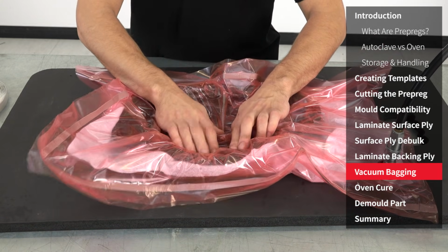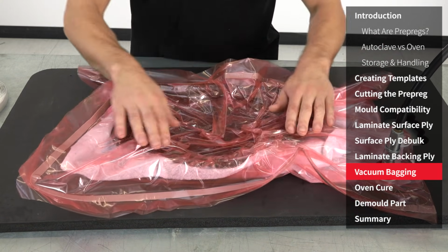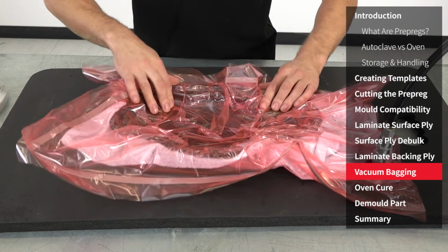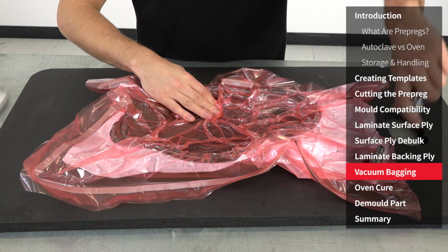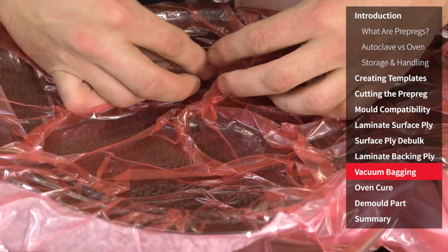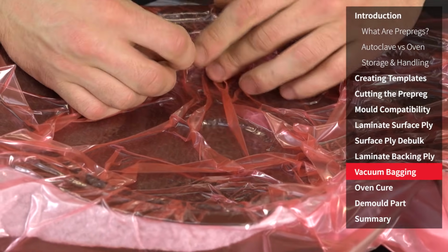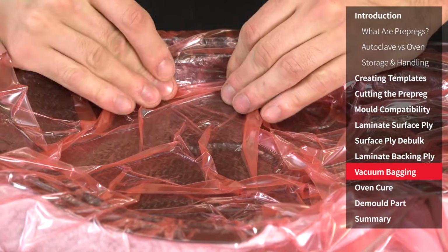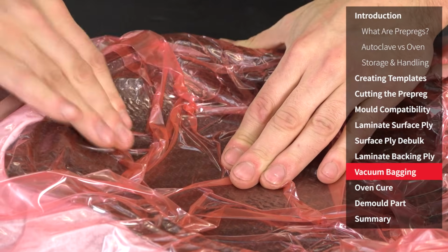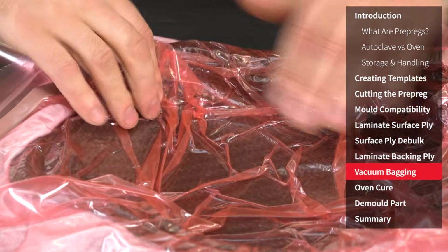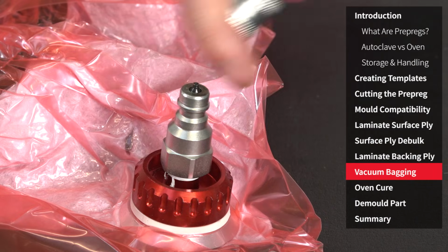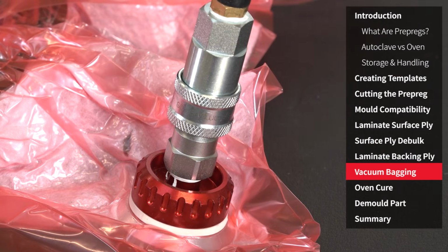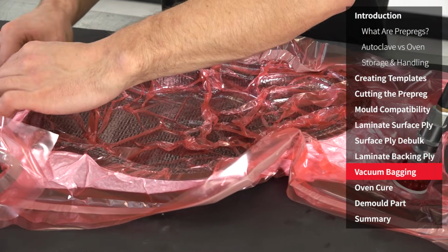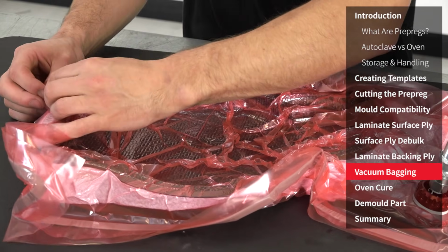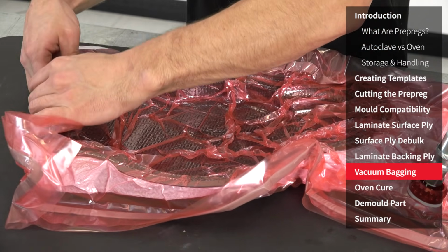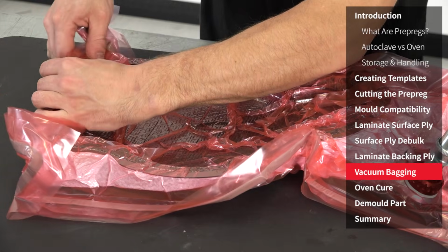As the vacuum is pulling down, the bagging film should be manoeuvred and manipulated so that it conforms to the laminate without having to stretch. You will normally need to disconnect the vacuum supply a few times to allow for repositioning before a full vacuum is pulled. Once you are happy that the bag is properly positioned, full vacuum should be applied and a seal checked for leaks. Once you think that you have the bag well down and perfectly sealed, it's recommended that a 10-minute drop test is conducted to ensure a perfect seal.